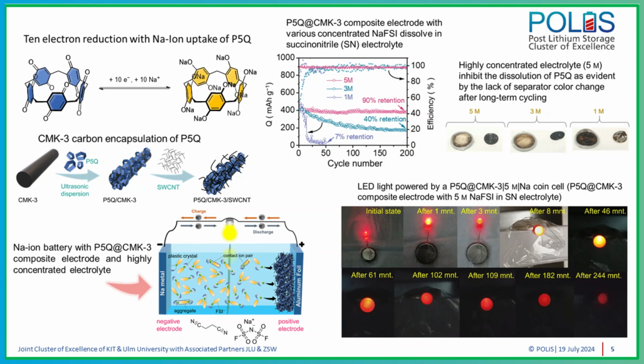With the progress of our research work, we found that physically mixing the conducting carbon material into our electrode was not helping us to improve the cycling stability of pillar-5-quinone and to get an improved electrochemical performance. So what we thought of is to first make a composite material with the pillar-5-quinone and a suitable conducting carbon. In order to do so, we have encapsulated this pillar-5-quinone with the highly porous mesoporous carbon called CMK-3 by a solution impregnation method. And towards the end, we have increased the electrical conductivity by providing a three-dimensional electrical conducting network by adding a small amount of CNT into the final electrode.